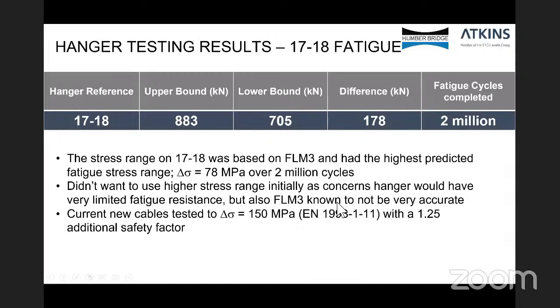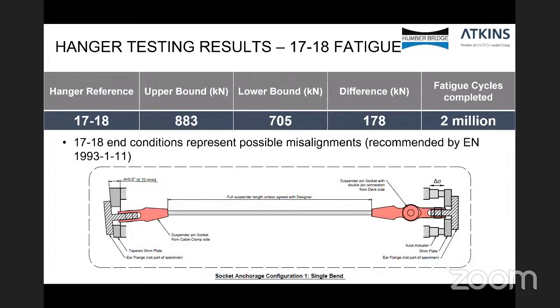Now, under the British standards or the Eurocodes, 1993 Part 1-11, if you were designing a new bridge today, you would test for a fatigue stress range of 150 megapascals. However, we didn't want to test for a very high stress range initially because there were concerns that the hanger would have very limited fatigue resistance and therefore would fail. So because of that reason, we first tested to the known fatigue load of 78 megapascals. We look to the next slide.